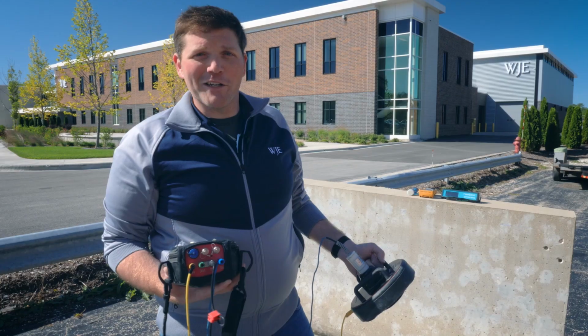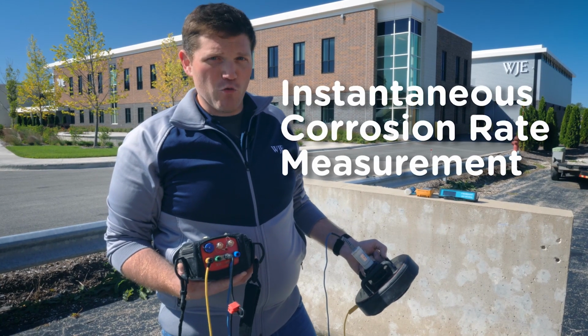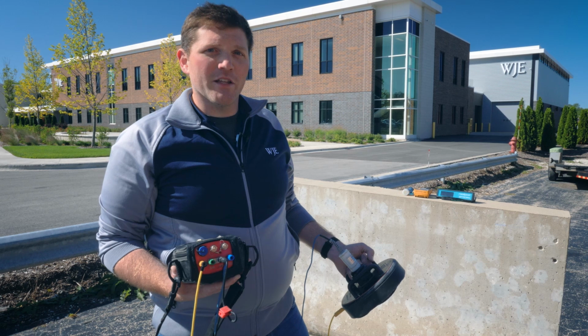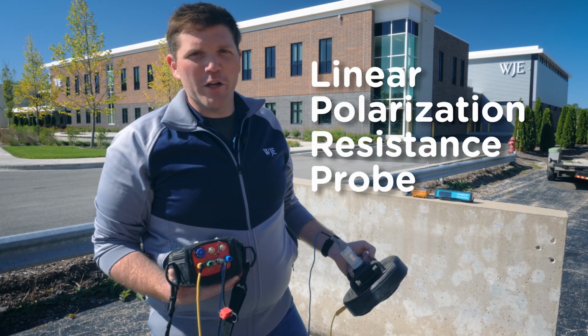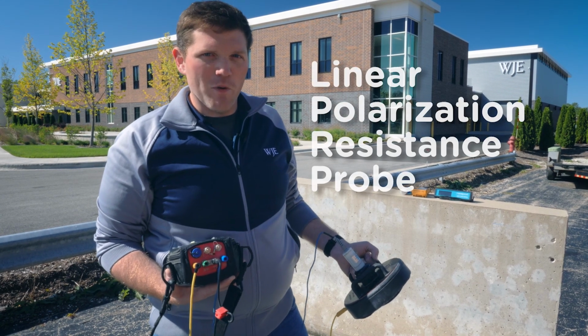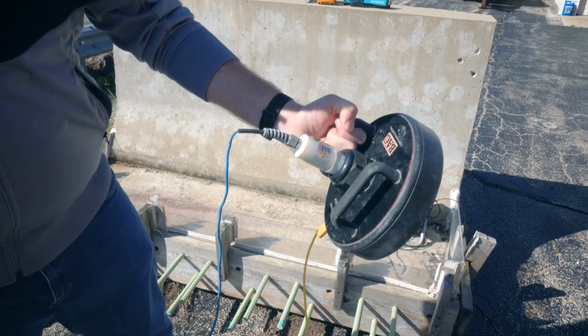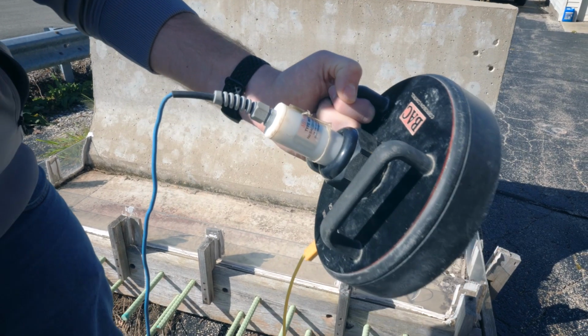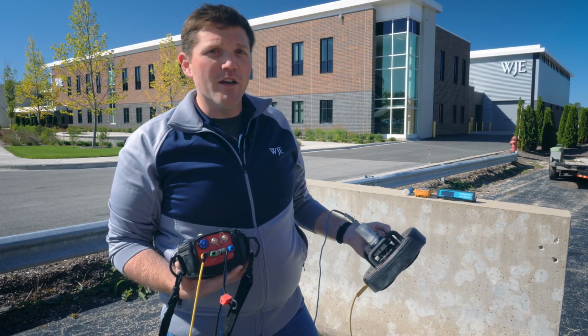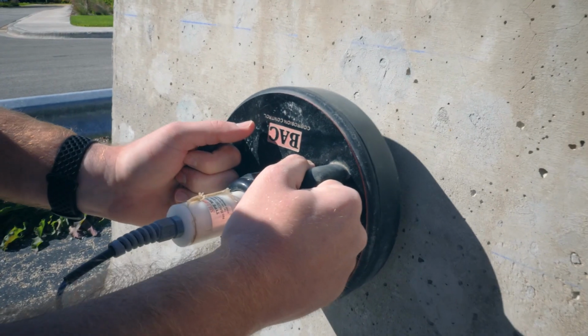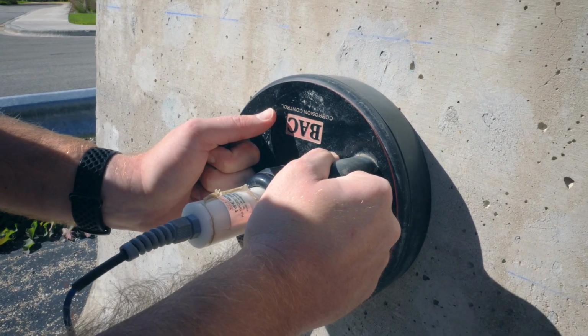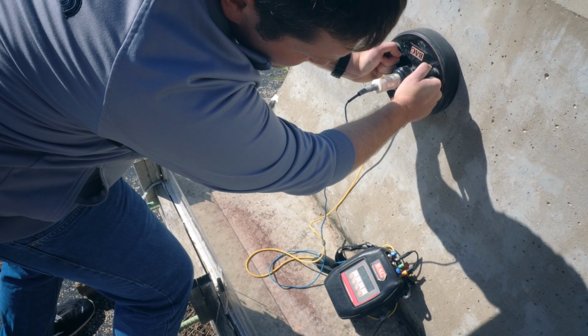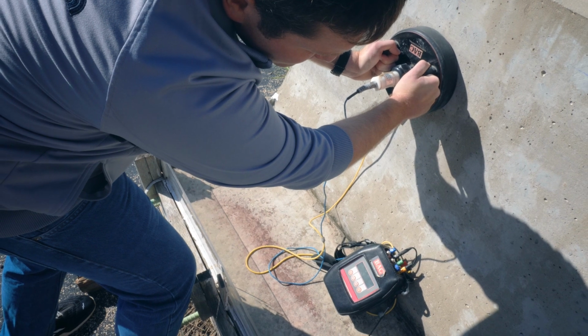The third method we're going to discuss is instantaneous corrosion rate measurements using the LPR probe, or the linear polarization resistance probe. This device uses a ring electrode and a half-cell electrode to create an electrical circuit with our embedded reinforcing bar. The results of this test give us an indication on how fast the reinforcement might be corroding and when we might see damage in the reinforced concrete structure.